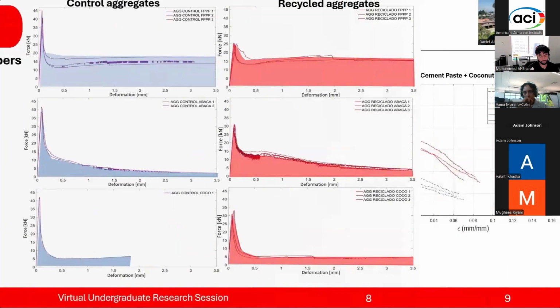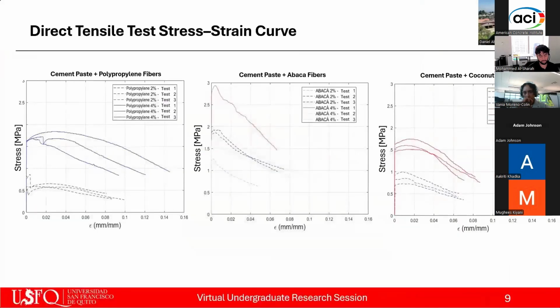The direct tensile test confirmed the same pattern seen in flexural behavior. At a 4% dosage, mixes with synthetic fibers show the highest deformation capacity and energy absorption compared to the natural fibers. However, maximum tensile strength revealed a different trend. At the lower dosage of 2%, natural fibers, especially coconut and abaca, outperformed polypropylene. At 4%, coconut and polypropylene reached similar peak strengths, while abaca achieved the highest tensile strength of all mixes. This gain in strength with abaca, however, came with reduced deformation capacity compared to synthetic fibers.